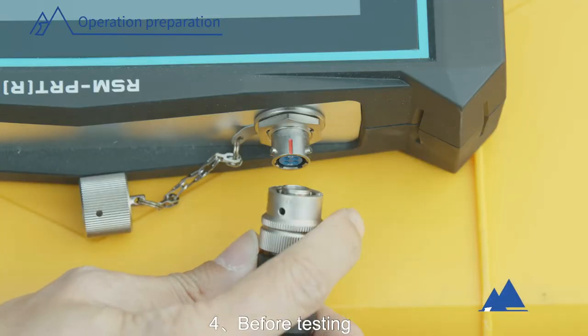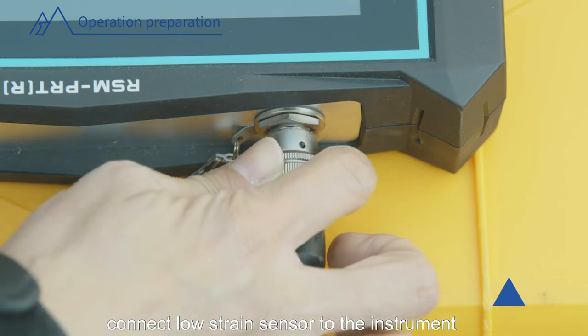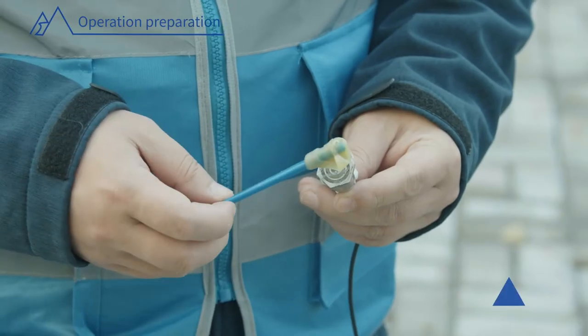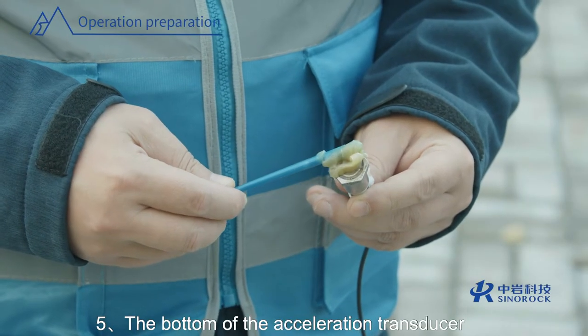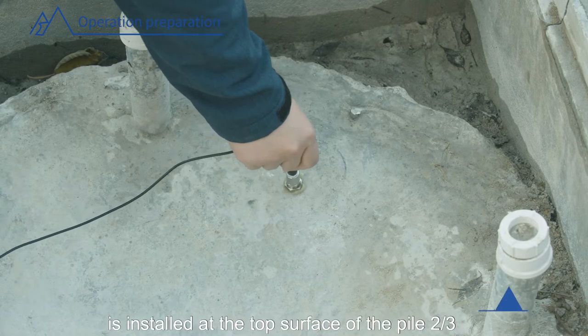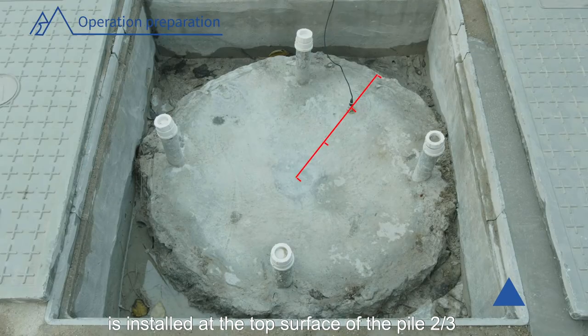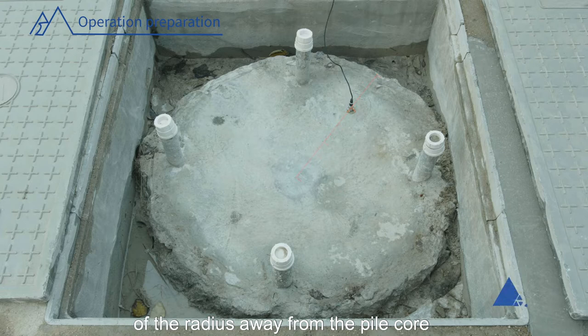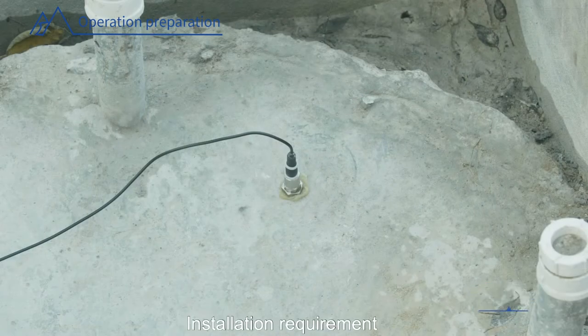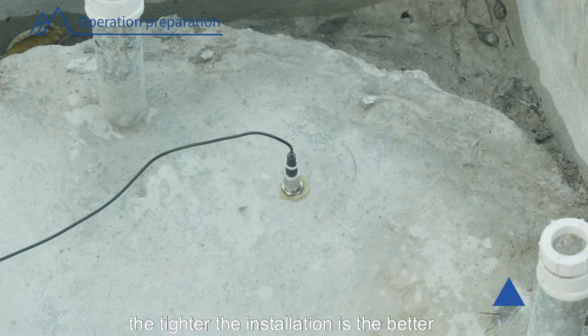4. Before testing, connect the low strain sensor to the instrument. 5. The bottom of the acceleration transducer is installed at the top surface of the pile, 2/3 of the radius away from the pile core, through butter bonding. Installation requirement: the tighter the installation is, the better.